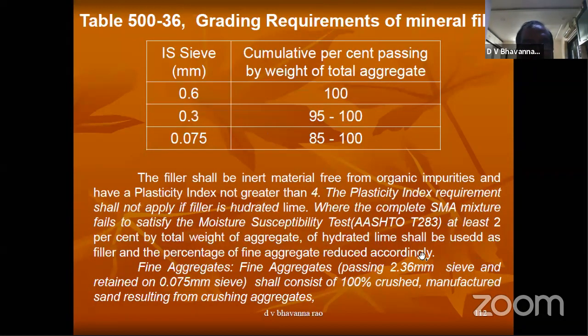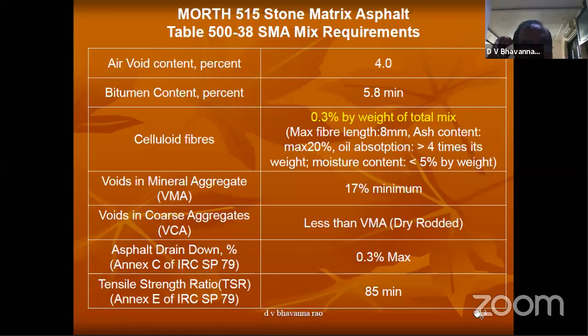Next, the downward turn side. Gradation for filler material. Next. Here, what is the difference between these, the BC, etc.? The bitumen content is 5.8%. Cellulose fibers are 0.3% by weight of total mix. These fibers are added. This is the difference between the DBM and VCA and SMA. And also aggregate sizes are more here. The voids in mineral aggregate is 17%.